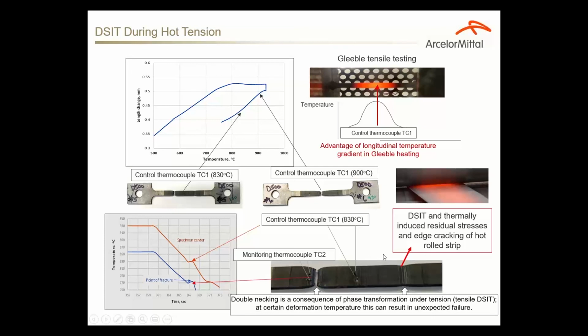Another application, again using the advantage of direct heating and thermal gradients, is studying dynamic strain-induced transformation during hot tension. Unfortunately, I already ran out of time. This is a very interesting application that we recently discovered, and it helps us to predict whether dynamic transformation takes place in this hot rolled strip, how it can affect edge cracking of hot rolled strip, or how it can induce the residual stresses that contribute to the defects of the sheet material after hot rolling.